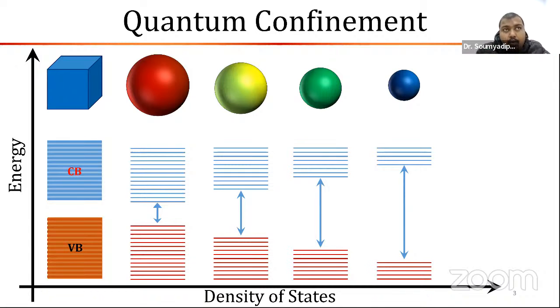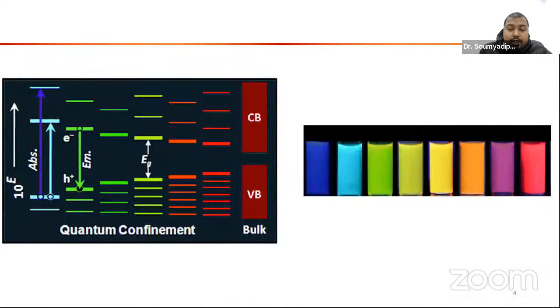For cadmium selenide, it was published by Professor Bawendi at MIT in 2000 or so, how the size of CdSe quantum dots, moving from 8 to 2 nanometers, changes the entire spectral range from red to blue. This is a picture of the quantum dot solutions from blue to red, as you can see.